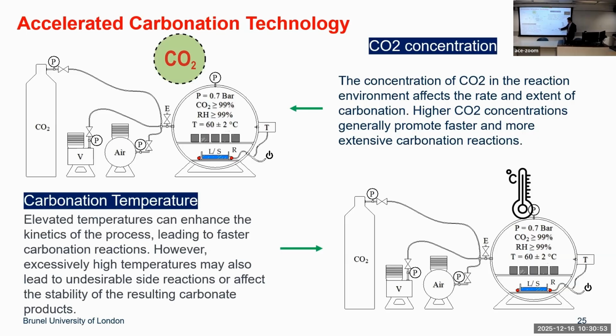And temperature as well. Usually we're seeing 50, 60 degrees. Normal temperature is probably not strong enough to generate the kinetics needed to improve the carbonation. But if you have an excessively high temperature, you may lead to undesirable side reactions and affect the stability of the carbonate.